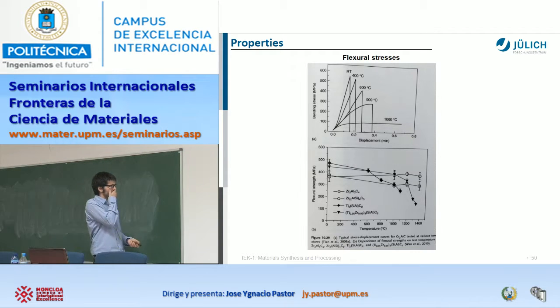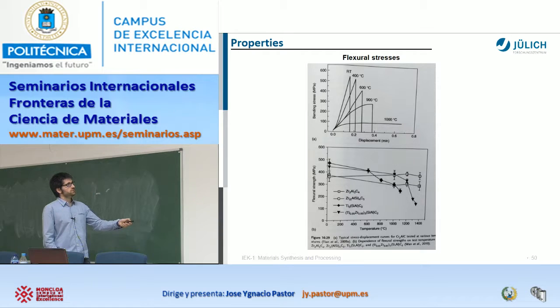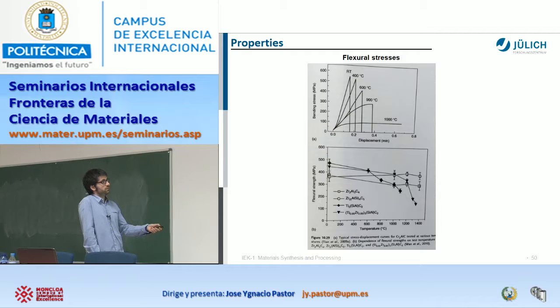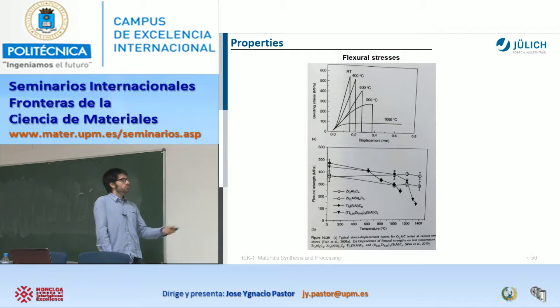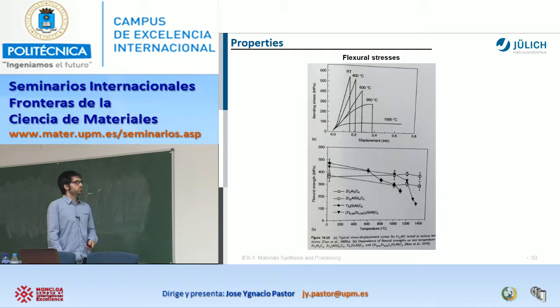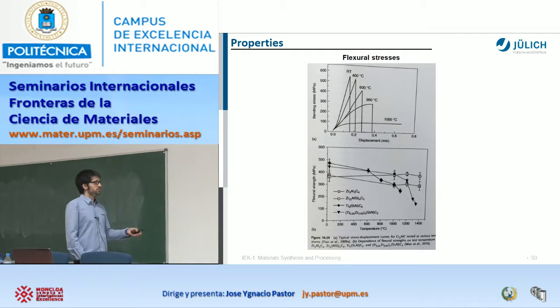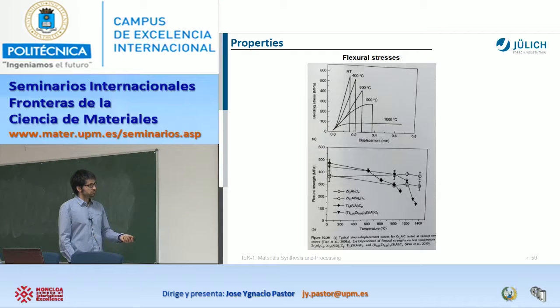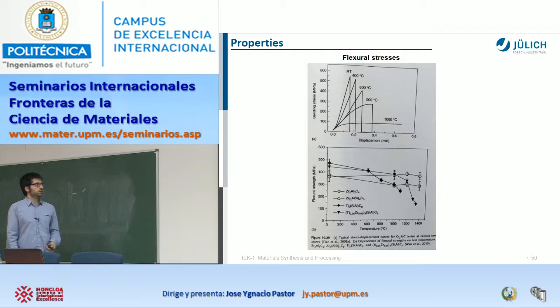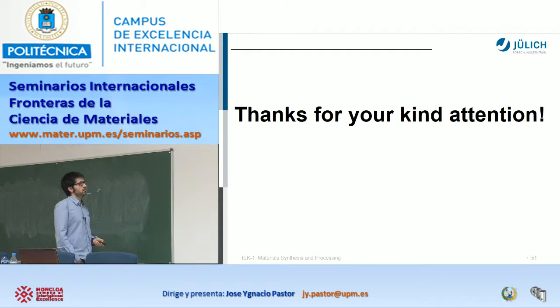And the flexural strength, again at room temperature the catastrophic failure, but if you increase the temperature, even the response depends on the application, but could be better. Here it is ductile, your material doesn't break directly. Okay, more examples also, if you incorporate some elements by solid solution in your structure, different response, but always at too high temperature it would result. Normally the threshold is around 1200, 1300, and for that temperature they respond quite well.